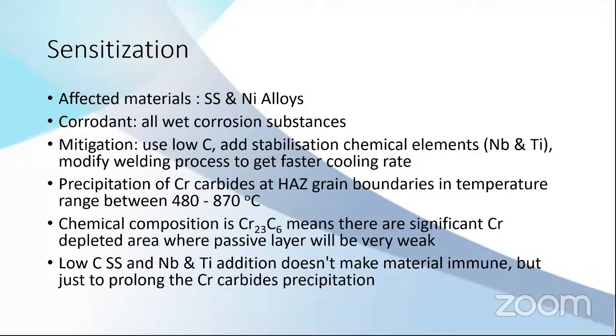And this is just information. Even if you use low carbon steel and addition of the chemical elements, it doesn't make it immune, but it prolongs the precipitation time. So if you have this equipment working at 500 or 600 Celsius for years, then I know, more than 5 to 10 years, then you may have this problem.